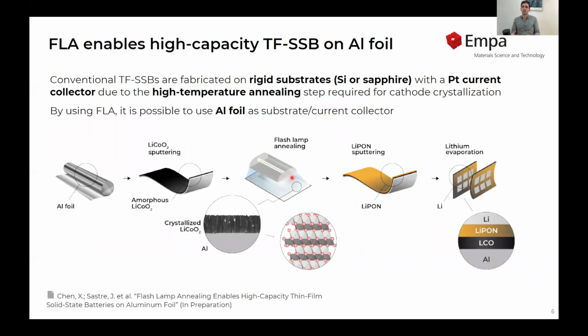So as I mentioned, one of the main advantages of these photonic methods is that we can crystallize cathode films on temperature-sensitive substrates. So I already said in the introduction, typical thin film batteries are fabricated on rigid substrates like silicon wafer or sapphire, and they employ a platinum current collector. So by using FLA, we try to demonstrate an alternative processing, basically processing a thin film battery on aluminum foil, which is a common current collector in the lithium-ion battery industry, and is cheap, flexible, lightweight, and convenient for an industrial process.